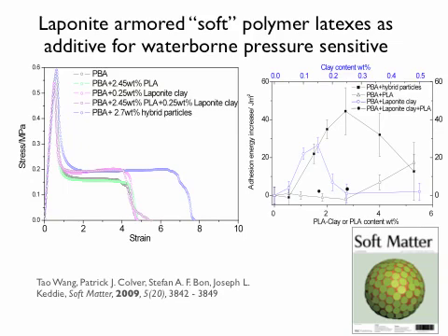And how do you measure the adhesion force of a sticker? Well, they do that with a machine that has a large metal sphere. So you cast the film of the sticker, the metal sphere comes into the sticker, and then you measure the pull-off force. So you just lift that big sphere up, and you check when there's no interaction anymore. So let's do that experiment. So you get a stress versus strain type of experiment.